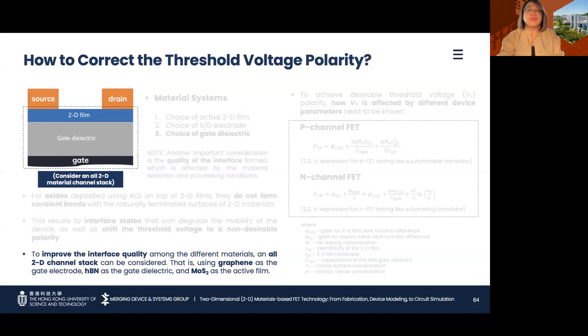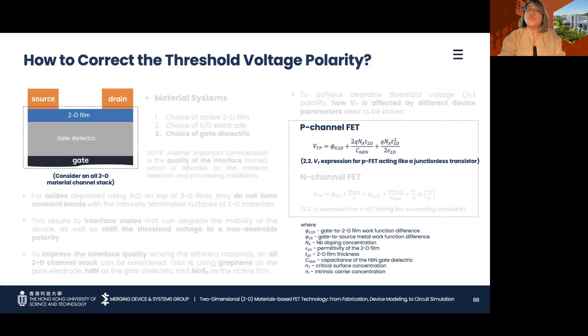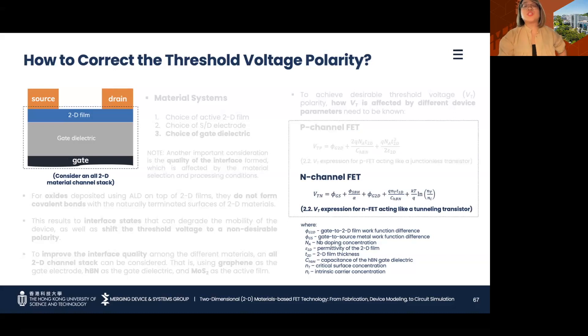In the following demonstrations, only the gate electrode and dielectric will change, but the choice for the active films and the source-drain electrode will not change. For the p-FET, since the 2D film is doped, it behaves like a junction-less transistor with thermionic emission as its main contact transport. For the n-FET, as the body is undoped and a finite barrier is present at the metal/2D interface, it operates similarly to a tunneling transistor, where the source metal Fermi level must first align to the conduction band edge at the 2D/dielectric interface to promote tunneling. The purpose of these expressions is to show the rationale for how we select the succeeding dimensional parameters, particularly for the 2D film and dielectric thickness.